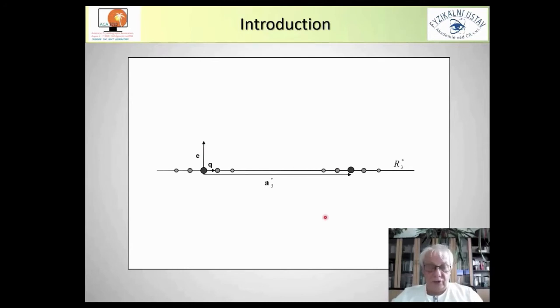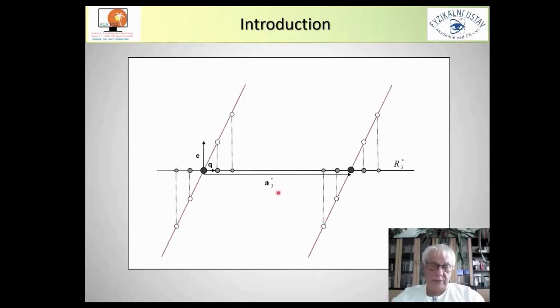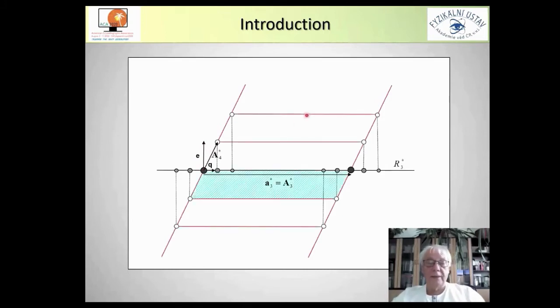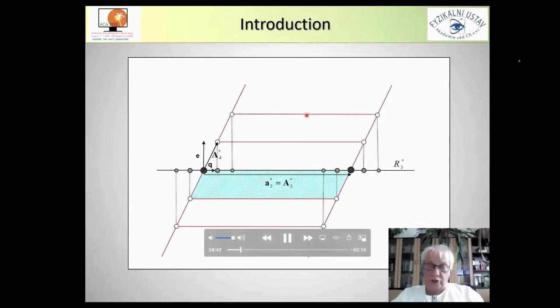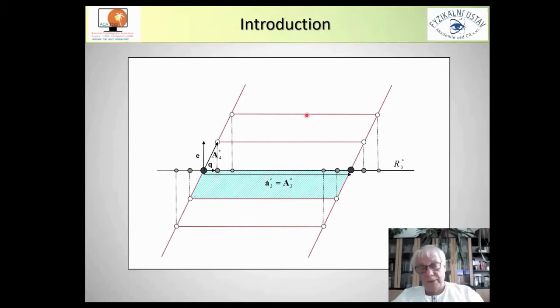Then we have a chance to move all diffraction spots out of this plane artificially and make new lattice vectors, where this a4 star is just the summation of these two q vectors, and now we already have a lattice. The lattice character in this artificial two-dimensional space means that the Fourier transform, which represents some diffraction experiment, will have translation periodicity. So we are in fact returning back to crystallography. We have again translation symmetry of our object.